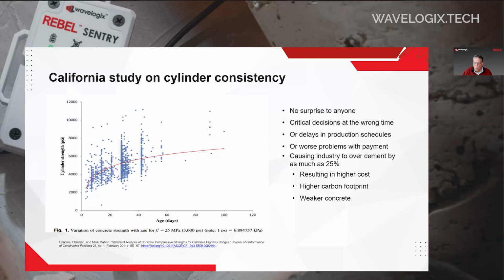It ends up, one of the things that happens when you're not really certain if your cylinder is right or going to give you the right data. But you need to keep your production schedule moving, and you need to be able to get paid, and you got to make sure that you hit the required strength. The industry over cements the concrete by almost as much as 25%. So they're adding more cement in to make sure that they get to the hardness they need, because they know that the cylinders may give them inaccurate results. And so what happens? It results in higher costs because cement is the expensive part of concrete. It creates a higher carbon footprint because it's the cement that's giving us a higher carbon footprint in the concrete.